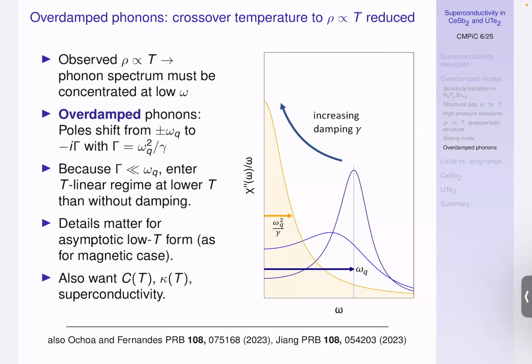Well, that now depends on details. What I'm just saying is the changeover from linear in T to T squared resistivity happens when the temperature reaches here. So below we would see T squared because basically chi double prime over omega becomes constant, just like it was for the underdamped response. But also what this does not yet take into account is that the response function itself will be different at different Q vectors. So there may be a question of dynamic exponents that you have to look into the details of the theory.